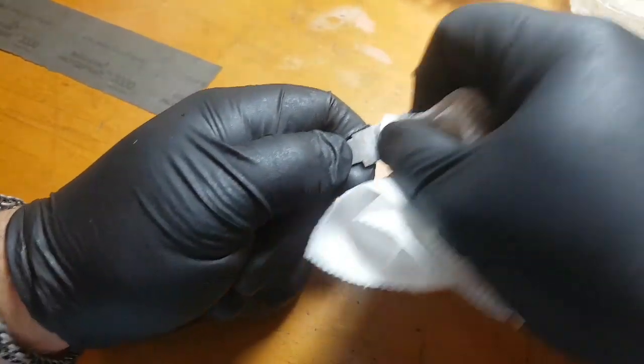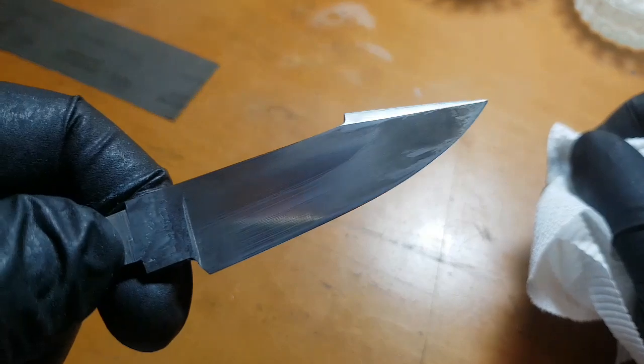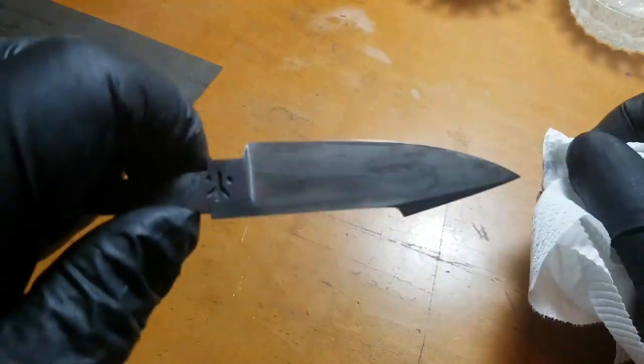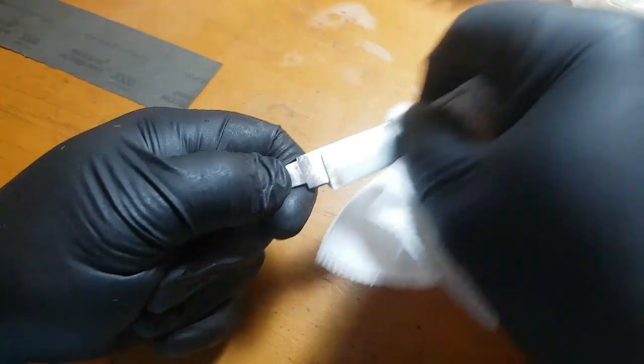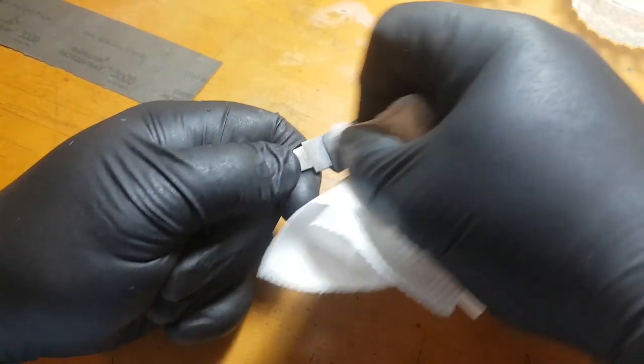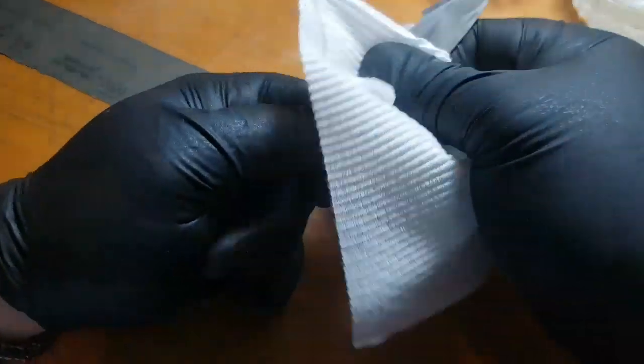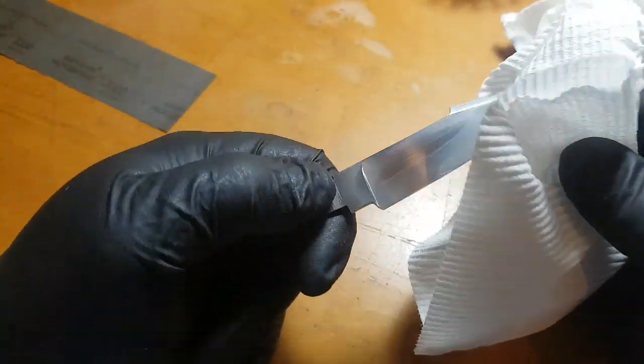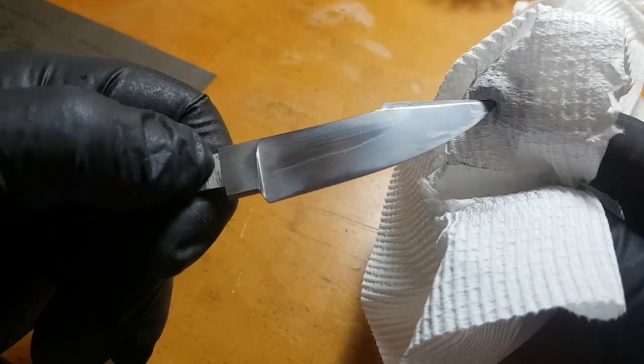One of the big things to remember is that you can't use a buffing wheel on a Hamon. You will literally strip the Hamon from the surface. You can buff before you try and go for the Hamon with the etching, but it tends to be less reliable than doing it by hand because you want the pores of the steel to be open.